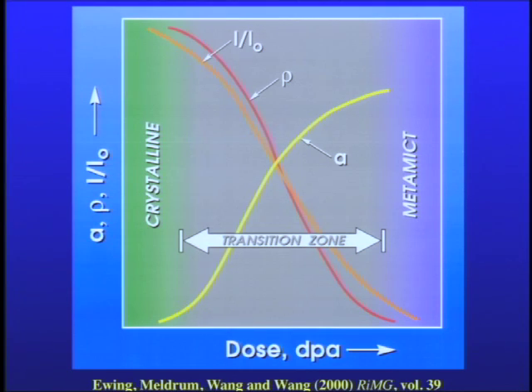The Bragg diffraction intensity drops as the material becomes amorphous. In other words, there's a radiation-induced transition from the crystalline state to the metamict state. And this is a function of dose. dpa is displacements per atom. That's a convenient unit for comparing materials.